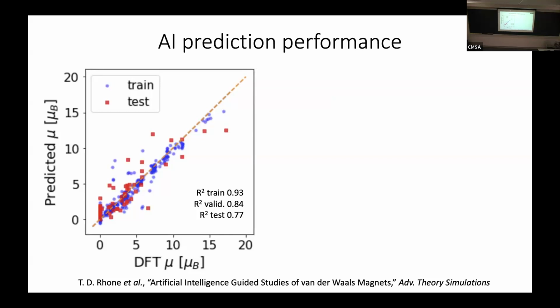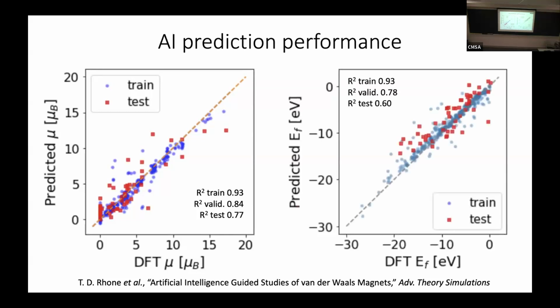That's for magnetic moment. Because we want to make these materials in the lab eventually and have them be some part of a device that helps some industry, we care about the formation energy and the chemical stability. And in this case, we can plot the calculated formation energy on the horizontal axis, the prediction of the formation energy on the vertical axis. And again, this dashed line is a perfect prediction line. Because all the points are falling close to the line, the model is performing pretty well.